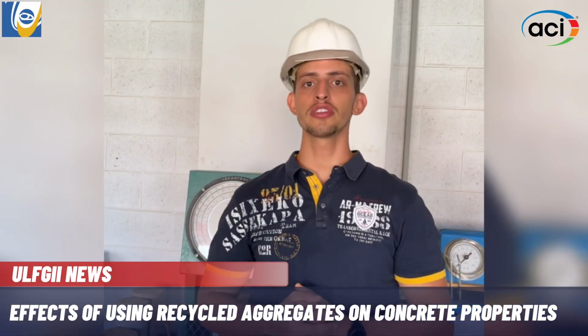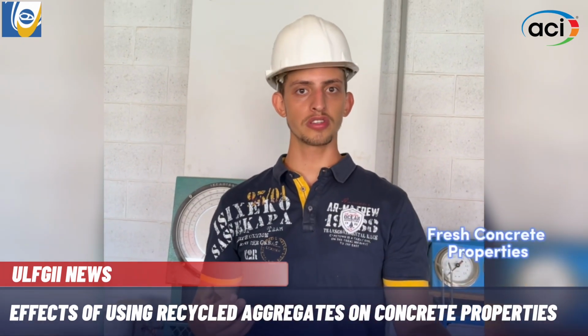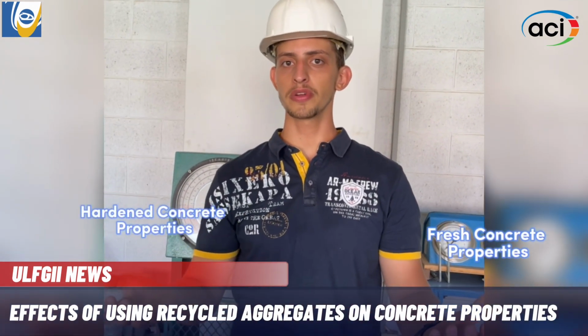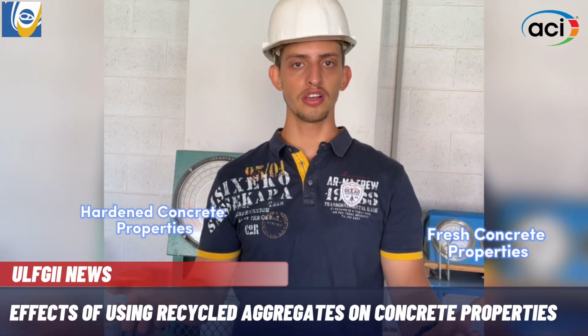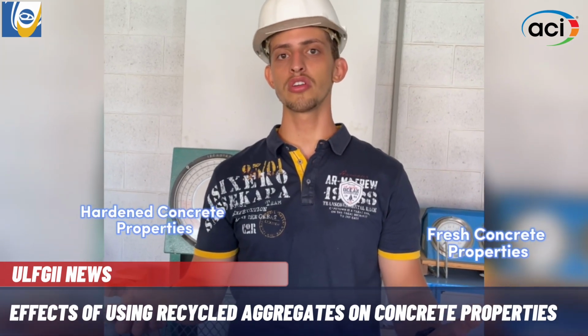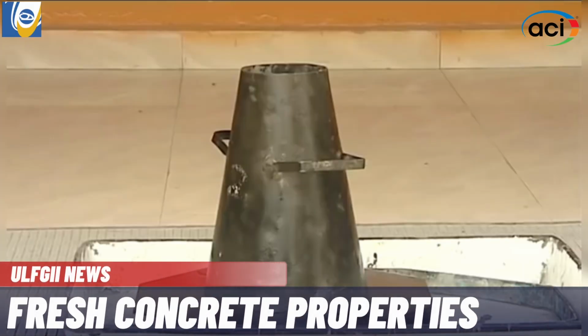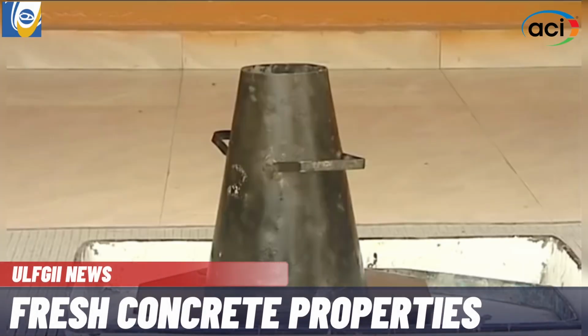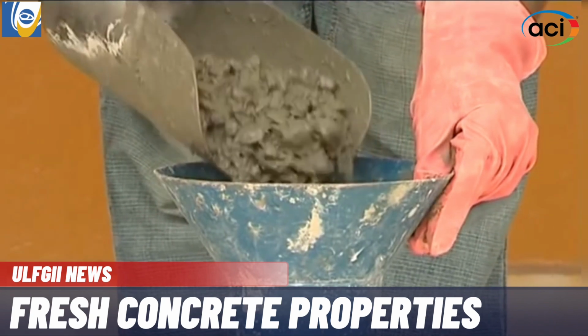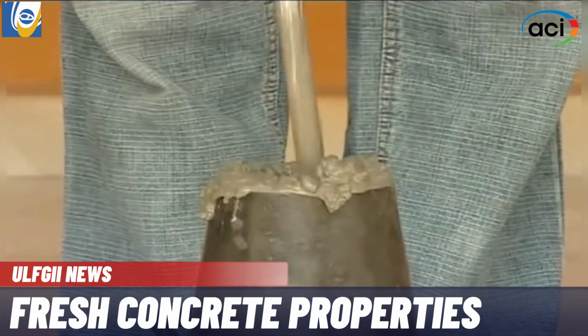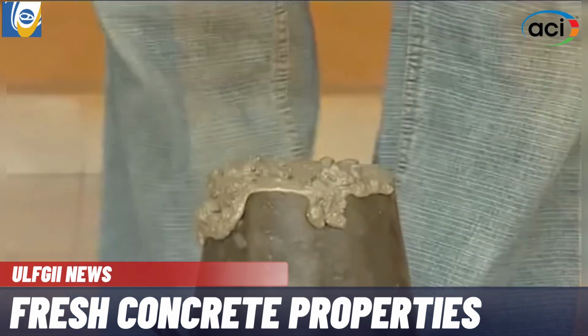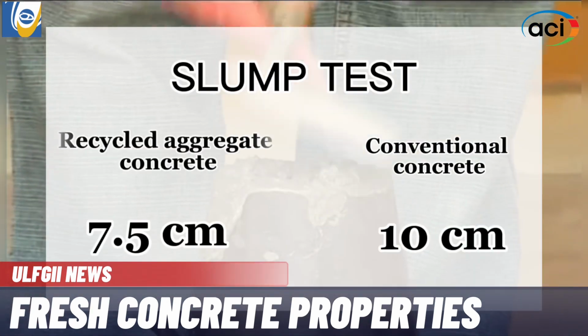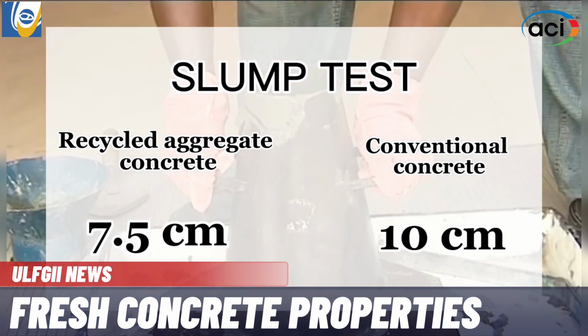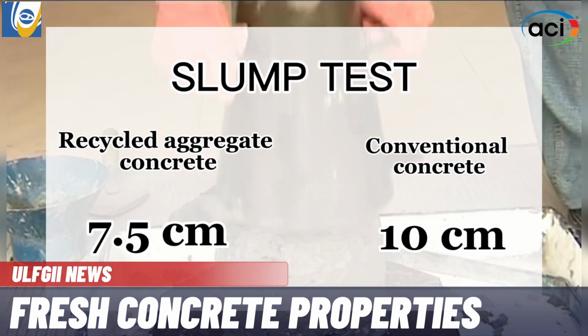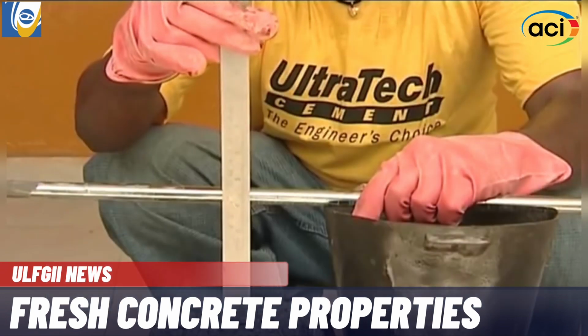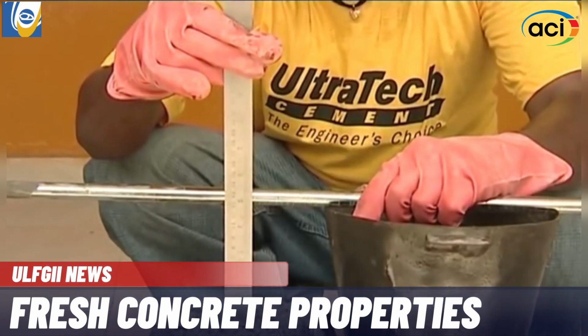Properties of concrete can be divided into two main sections. Fresh concrete properties such as workability, and hardened concrete properties such as compressive, tensile, and flexural strength, durability, and modulus of elasticity. The workability of fresh concrete is a very important property, which controls various other properties of concrete, such as density and strength. The slump of concrete containing recycled aggregate is lower than that of conventional concrete. It was observed 7.5 cm of slump for concrete containing recycled aggregate, while that of the conventional concrete was 10 cm, and that is due to the higher water absorption capacity of recycled aggregate.